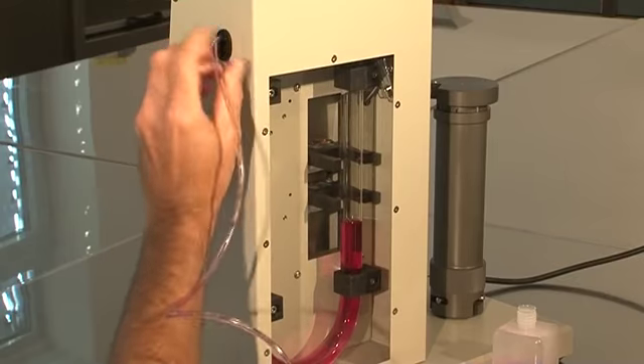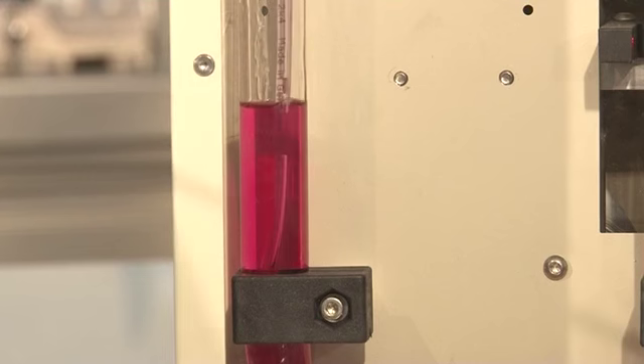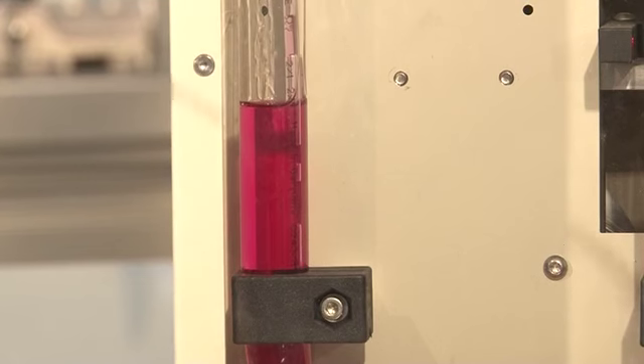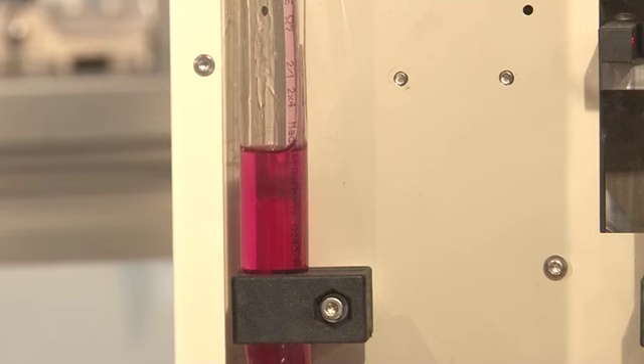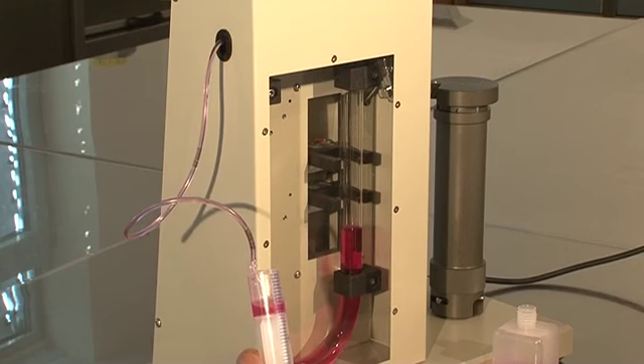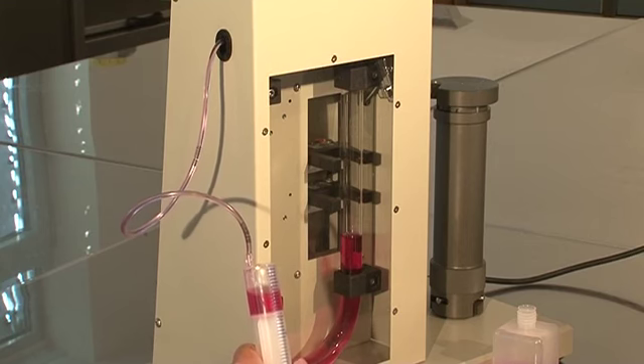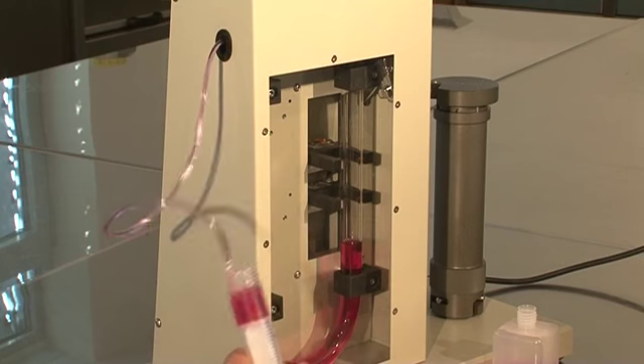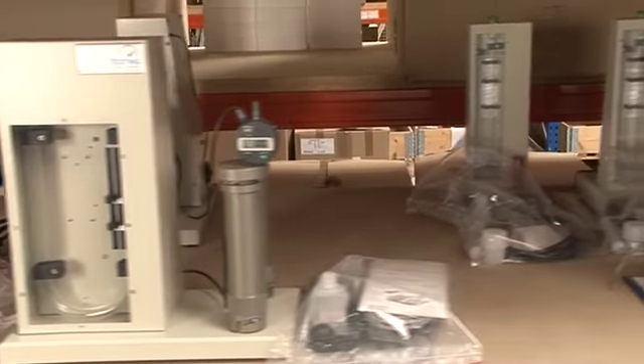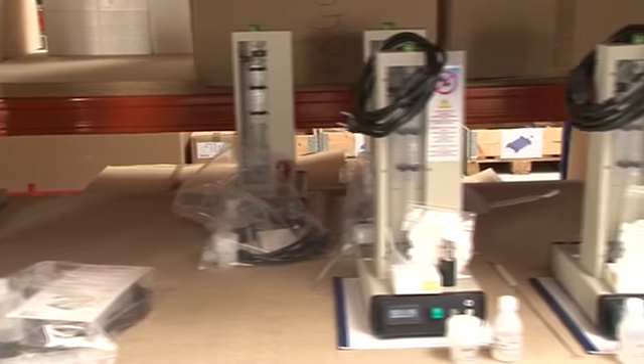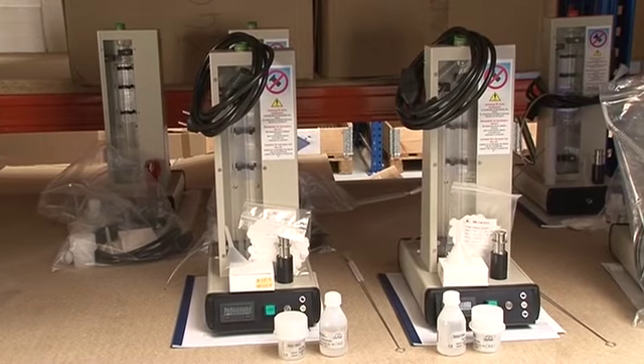If the electronic Blaine device has to be shipped, repaired or disposed of, the manometer liquid must be removed, otherwise there is a risk that the electronics could be destroyed. The liquid should be sucked out with the suction syringe. Never attempt to pour out the liquid. The device may be returned to the manufacturer for repairs or factory calibration.